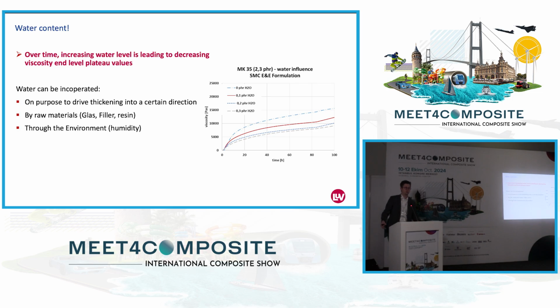Or if they add thixotropy additives to the resin, there are also solid and liquid ones. And the liquid ones incorporate water into the formulation, sometimes on purpose, sometimes by accident. And here, same curve, it's always the same for us, so it's easy to identify. You see that the water content, even 0.3 phr or 0.1 phr, leads to a totally different thickening.